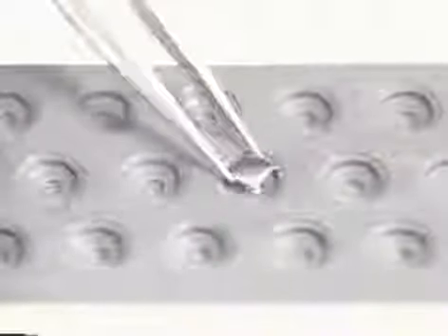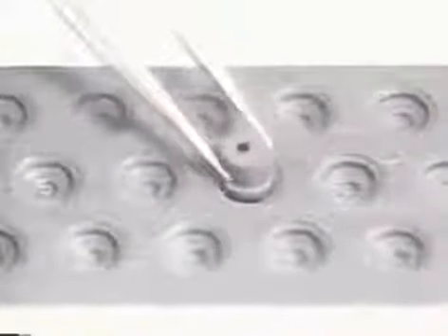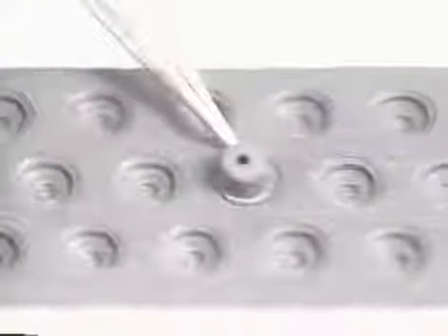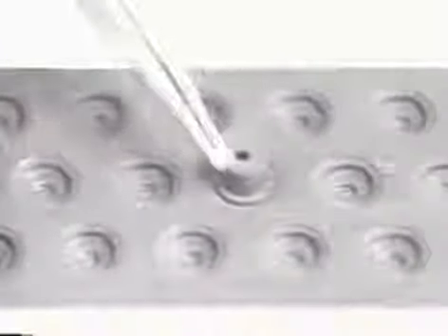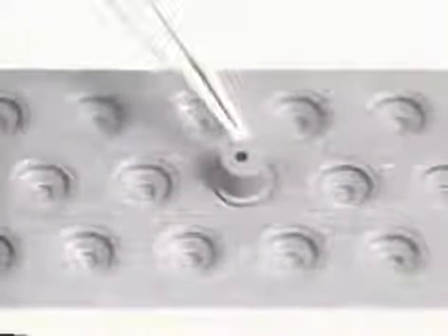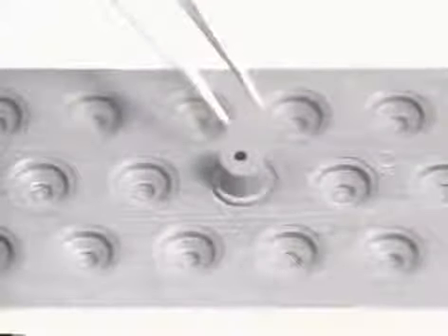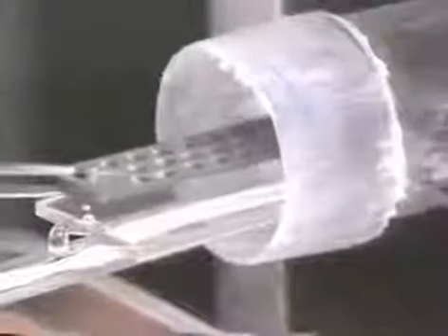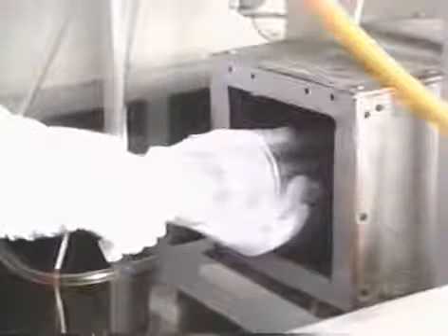To make an alloy transistor, indium particles are set in a vessel made of very high purity carbon graphite. On top, we place a 3 millimeter by 3 millimeter piece of germanium with a thickness of 0.5 millimeters. Finally, we put down a cover with a hole in it, and then we drop particles of indium from the hole onto the germanium. We repeat the delicate work for as many transistors as there are. In this state, we gently slip it into the furnace. Transistors are made for the number of holes exposed on the graphite plate, with variations occurring in the characteristics of each.